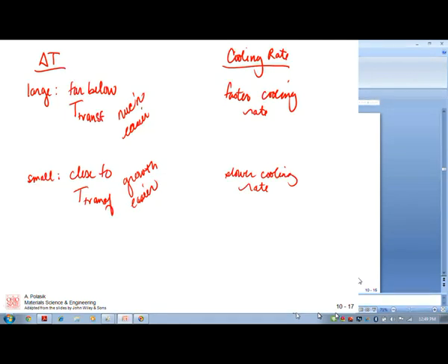What's happening when we make a steel component or a steel microstructure, when we process it, we're cooling it. And that cooling has a path, right? We can get it from 800 degrees C down to 25 degrees C a lot of different ways. And the path we take determines the final microstructure. Because at room temperature, diffusion is almost impossible.